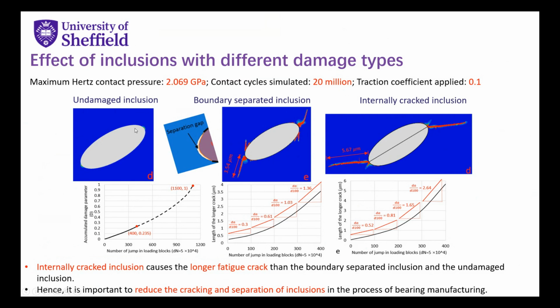If we look at the results, we can find it doesn't have any damage at the tips of the inclusion in this undamaged inclusion modeling, but when it has the boundary separation between the inclusion and the steel matrix, it has a fatigue crack here. It also has a fatigue crack here when the inclusion is internally cracked. If we compare this boundary separated inclusion and the internally cracked inclusion, we can find that the internally cracked inclusion causes a longer fatigue crack than the boundary separated inclusion. That means internal cracking of the inclusion is more harmful in subsurface rolling contact fatigue.